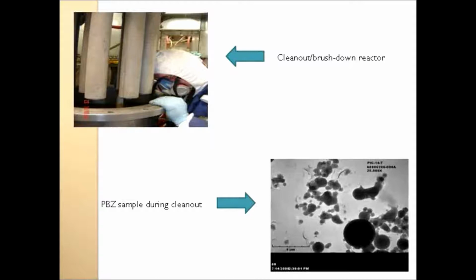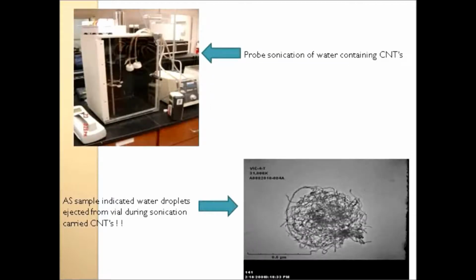Another interesting finding, and we find these things on occasion: sonication of just a small vial of material, water with carbon nanotubes inside of it. Many times people would dismiss the fact that anything could come out of it. It's in liquid. How could it become released? Well, we were surprised as well when we sampled inside of that chamber that holds the sonicator.